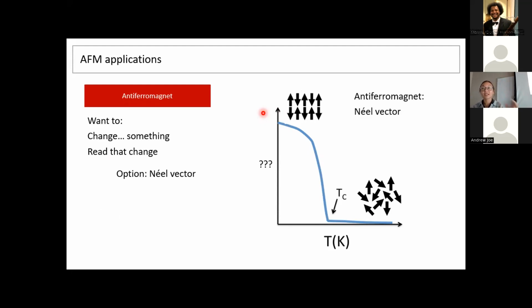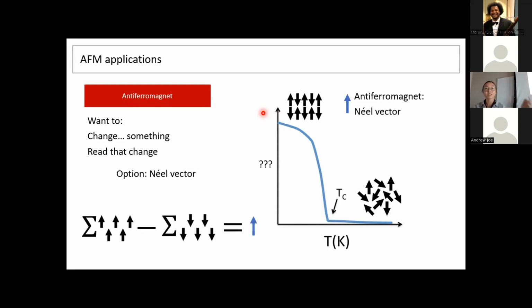So if now, instead of adding up all of our spins, we add up half of them, and then we subtract the other half, then we get something that's going to be finite and large when we have antiferromagnetic order, and it's going to go to 0 when we have a paramagnet. Because with a paramagnet, if you take half of them and you add them together, that's going to be 0. If you take the other half, add them together, that's still 0. 0 minus 0 is 0. So with the antiferromagnet, it works out very nicely.